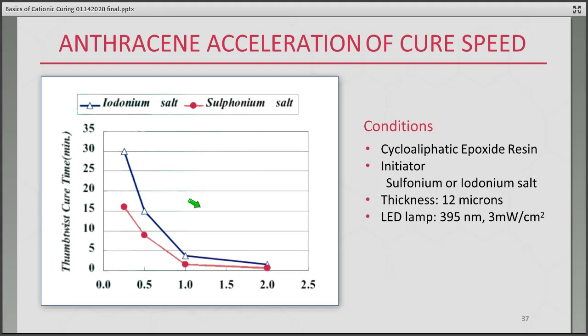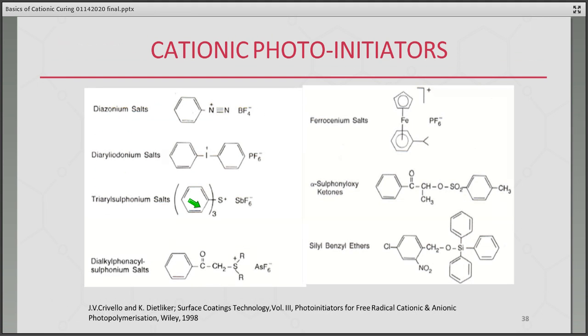It can work in thick films because the long wavelengths of light are what usually reach the bottom of a thick coating, and most of the photoinitiators are not sensitive to those longer wavelengths. However, anthracene derivatives are sensitive, so it will absorb the light at the bottom, near the substrate of a thick coating, transfer that energy to the photoinitiator, and now you kick off that photopolymerization and are able to cure a thick coating. So that's how it works with thick curing. These are really nice tools to have in your formulating toolbox for both cure speed and thick coatings.